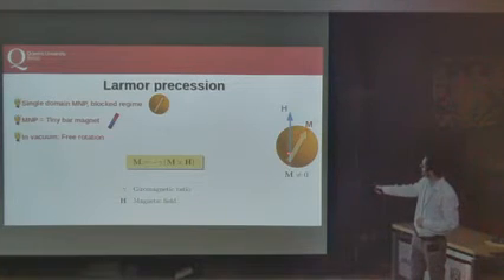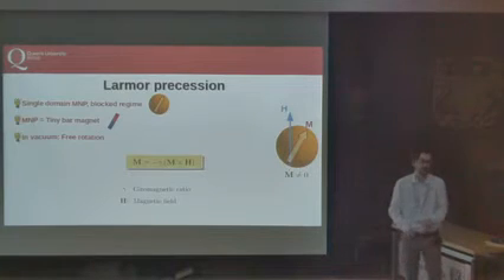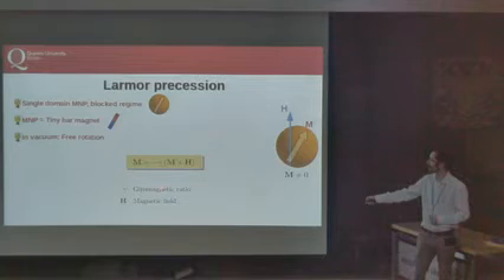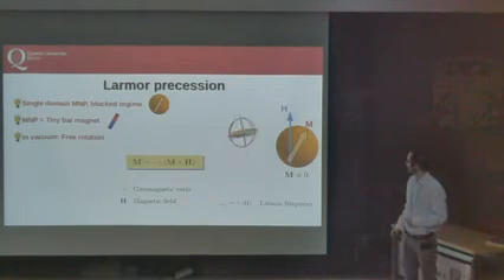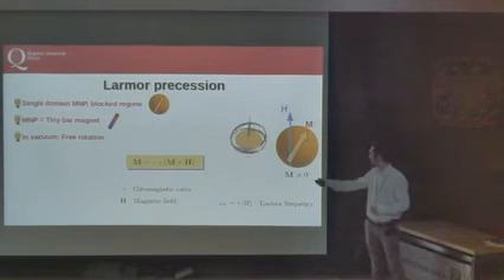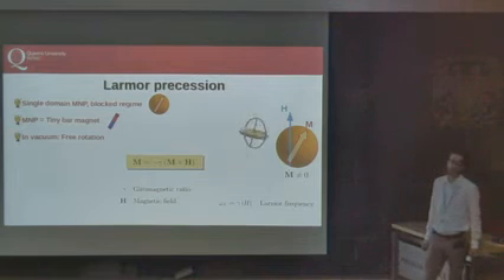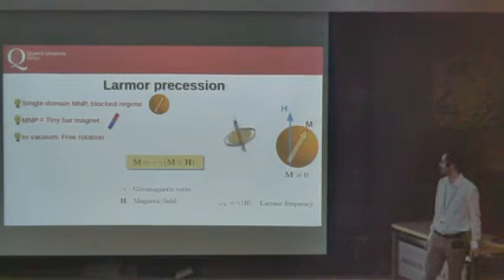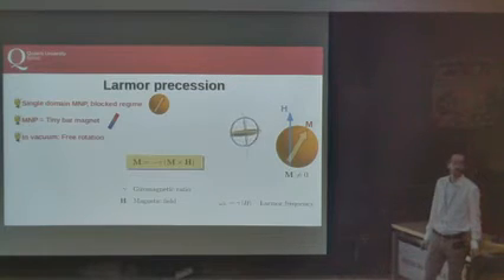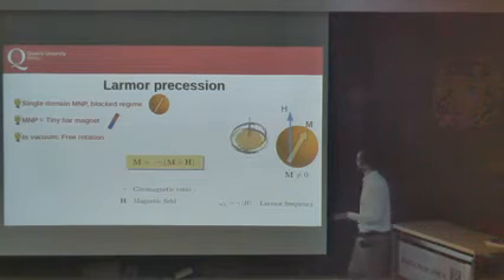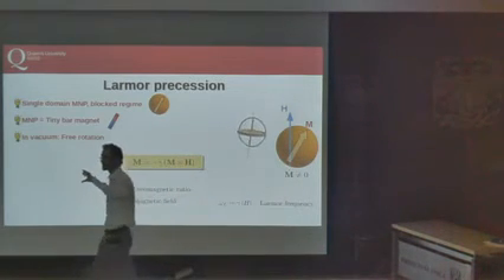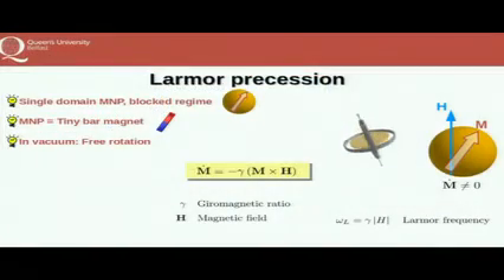It depends on the cross product between the external field and the magnetization density of the nanoparticle, through the gyromagnetic ratio. And the solution of this is precession, the so-called Larmor precession. The frequency of this precession can be high and is proportional to the modulus of the external magnetic field. This is a very simple motion. The magnitude of the magnetization vector does not change, it just precesses. But it will do that forever. Without any means of dissipation, without friction or viscosity, it will keep rotating about the axis.